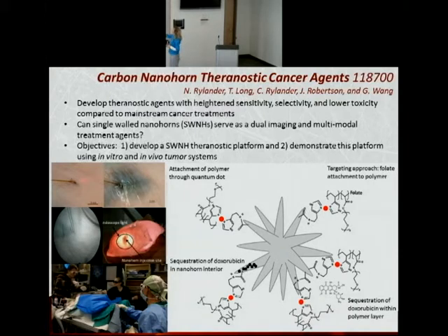So what you kind of see up here, first we looked at the optical spectrum. When we have nanoparticles or nanohorns, quantum dots and their conjugate, we see that our conjugate has characteristics of both quantum dots and the nanohorn. We have this characteristic absorption at wavelengths less than 500 nanometers. We also look at our fluorescence here. Our conjugate has a shift in fluorescence as compared to the quantum dots, so that's looking very promising.